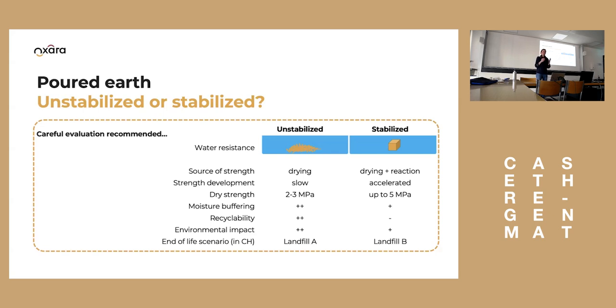In general, we say that poured earth has a compressive strength between 2 to 3 megapascal if it's unstabilized. And if it's stabilized, it can happen that if you use a low stabilizer dosage, you first disturb that clay matrix, and then you lose strength, and you need to dose at a high dosage to increase the strength higher than when it's unstabilized, because you first disrupt this clay network when you introduce a stabilizer. So, in general, it's not the most efficient to use stabilization only because you want a high end strength, because then you often go into high stabilization dosages.